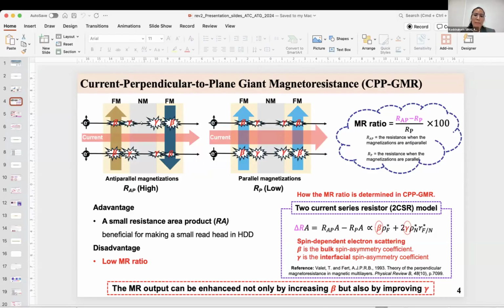If you use magnetic materials, the purpose of using the ferromagnetic layer is that we try to use half-metallic materials, because we need the high spin polarization to keep the spin orientation. So when you switch the magnetization, if you have a magnetic spacer, that magnetic material will disturb the spin moment when we transfer the spin accumulation from one side to the other side. Yeah, maybe this affects the MR ratio, maybe reduces the MR ratio. This is my understanding. Thank you.